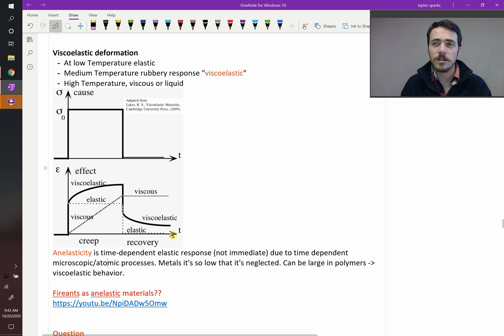It's not that simple in viscoelastic and anelastic materials. In a viscoelastic and anelastic thing, it's time-dependent. You can get this time-dependent increase where it initially strains a little bit, but if you hold it, it keeps on straining and it sort of asymptotes to a value. And then when you kill that stress, it doesn't drop all the way down. It drops to here and then it slowly decays back towards zero. That's an example of anelasticity or viscoelastic behavior.